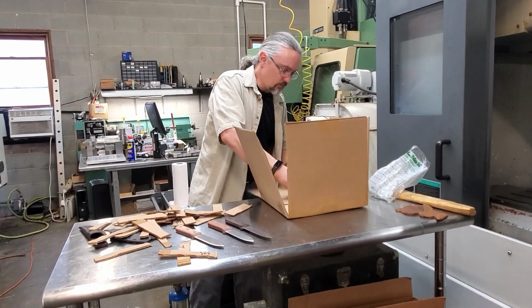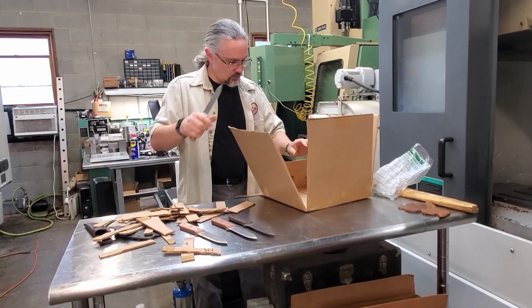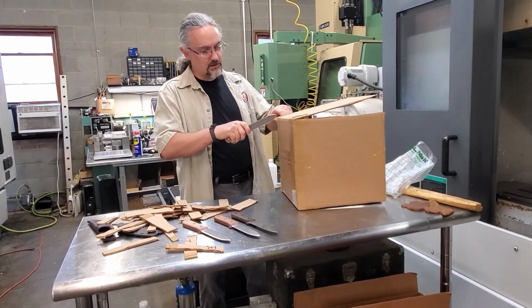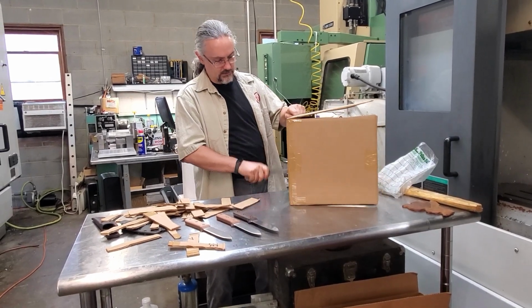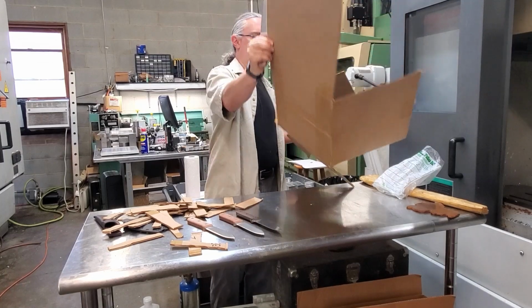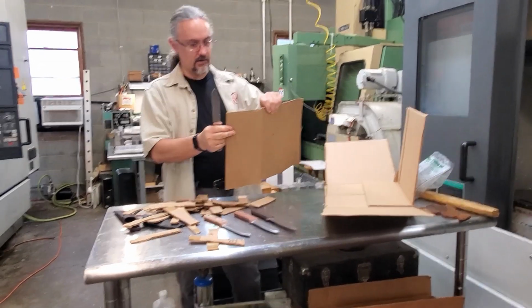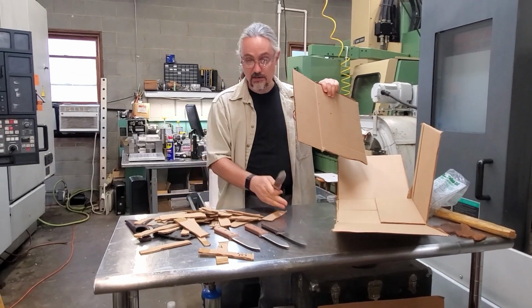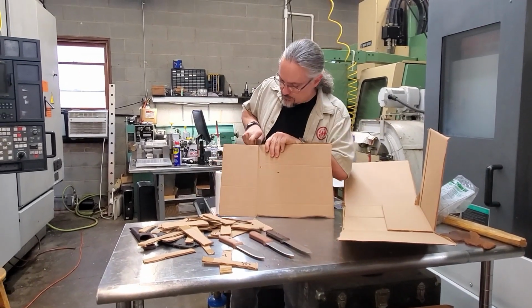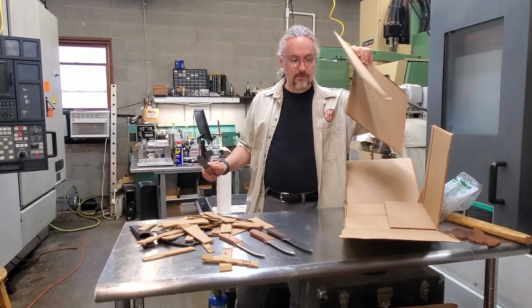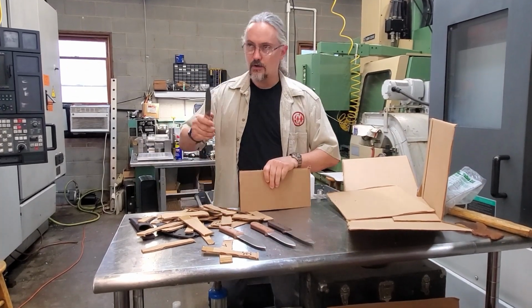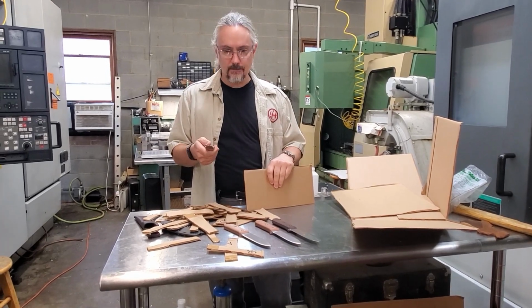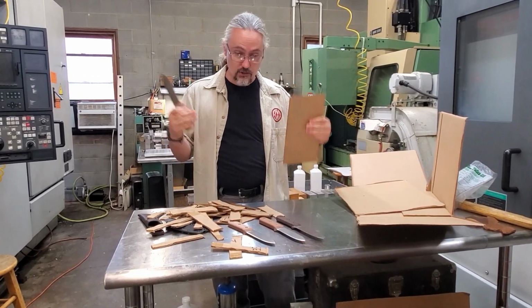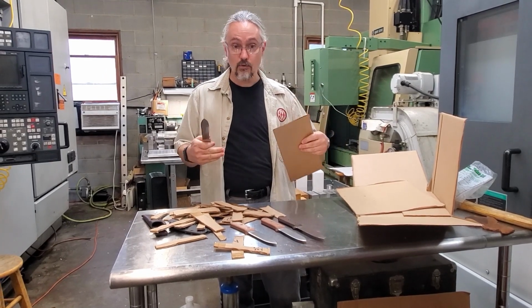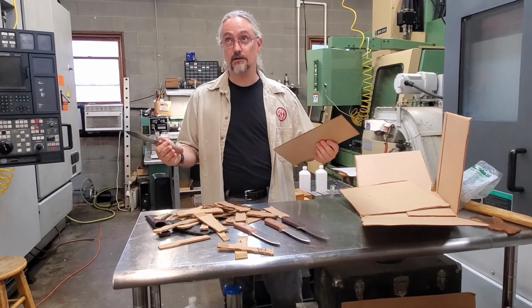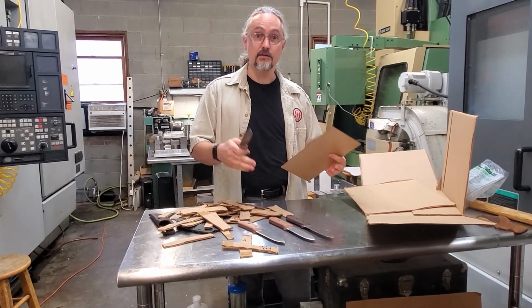And so with the low temper tweaks, there's a couple things you've got to do differently. You're going to have to address retained austenite with some other mechanism other than just hitting that secondary hardening hump to convert retained austenite. And so quench rate becomes more important. Quench rate matters for a couple of reasons. One, the faster you quench, you're maintaining higher strain energy going into martensite finish. You're going to be able to convert more of that retained austenite, or it's not retained austenite at that point, it's just austenite, into martensite.